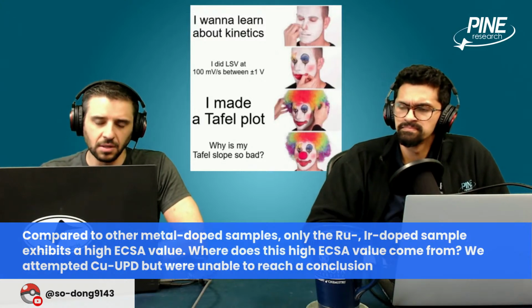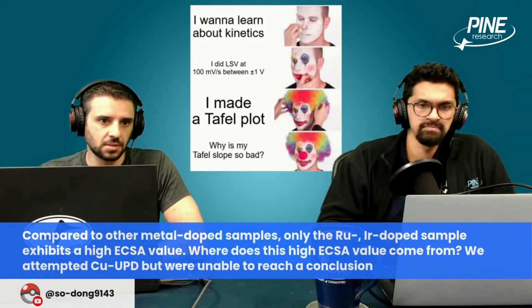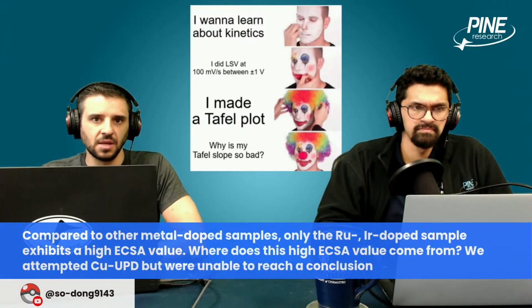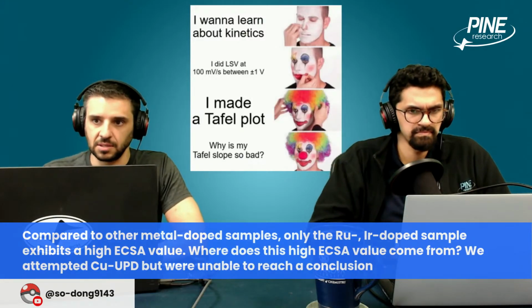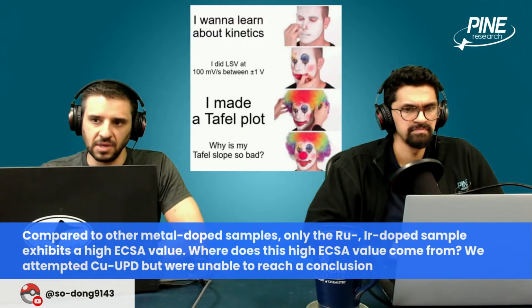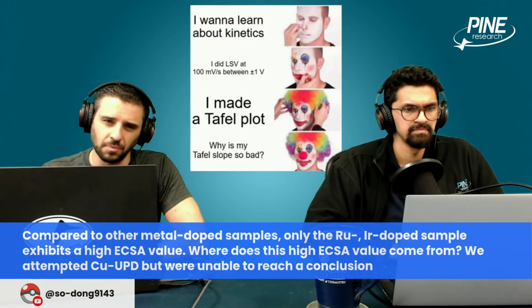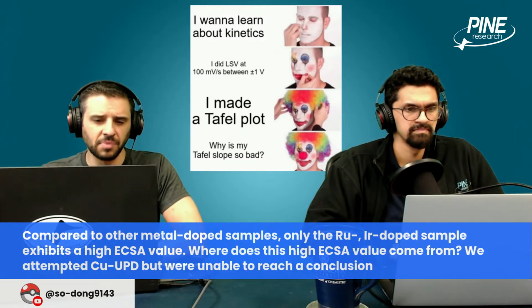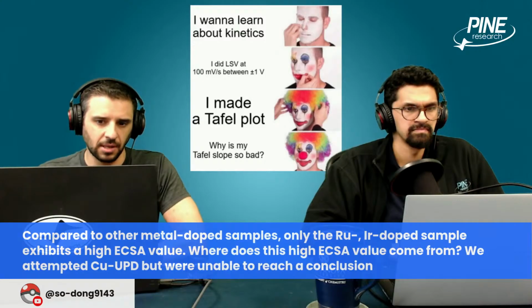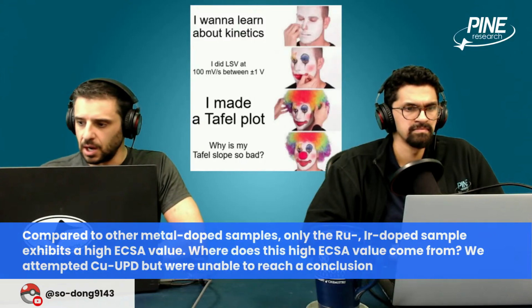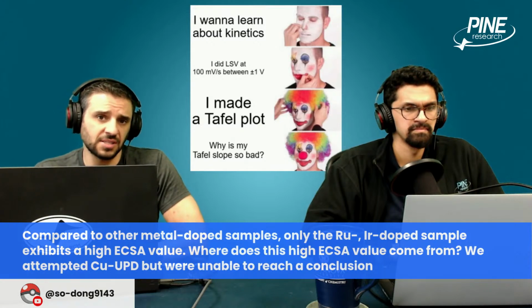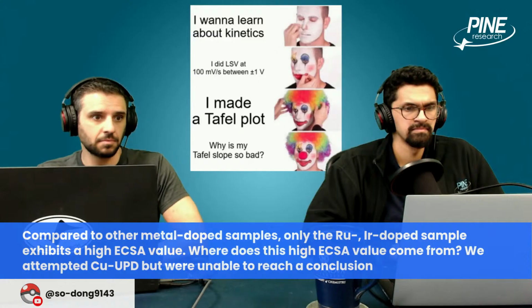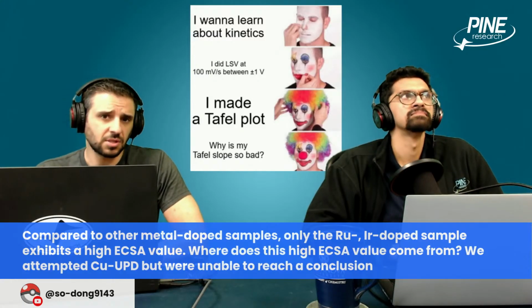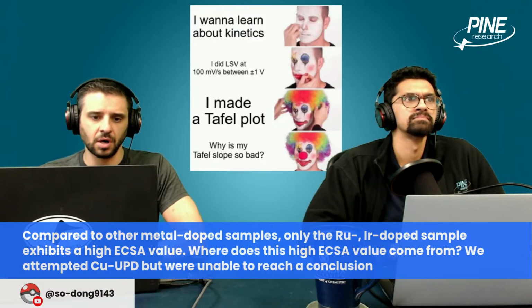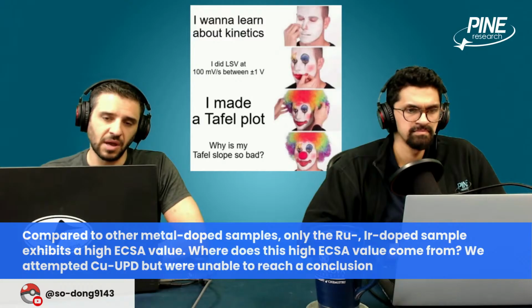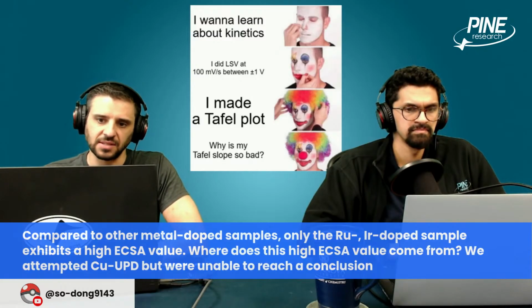Ruthenium is a noble metal. Ruthenium is quite a nice electrocatalyst in a lot of cases. It performs very well. It's pretty electroactive. It's usually used in a doping capacity because pure ruthenium isn't really workable the way other metals are. But people use ruthenium palladium or ruthenium platinum, or as you are, ruthenium doped. From that perspective, I'm not surprised you're getting a good ECSA with ruthenium or iridium. They're great electrocatalysts. So those are the two things that come to mind. But I don't know that I can speak much more specifically without knowing more details about your experimental process.